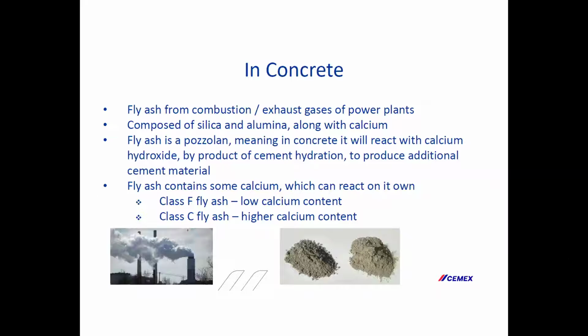So in concrete, and as Danny explained, from a coal plant, you get the fly ash that comes out the exhaust gases from the combustion process, and the bottom ash would come out the bottom. But fly ash is composed of silica and alumina along with some calcium. And as he mentioned, it's a pozzolan, which means that on its own, it might not be that reactive, but the silica and alumina from it will react with the byproduct of calcium hydroxide from cement that'll produce more cementitious